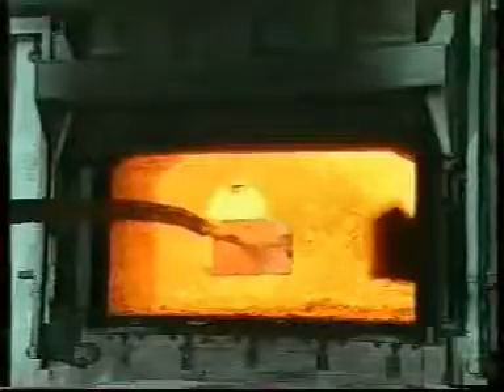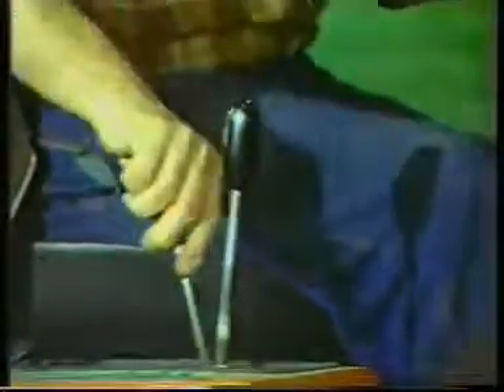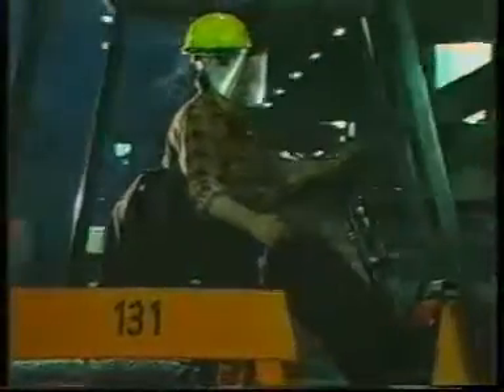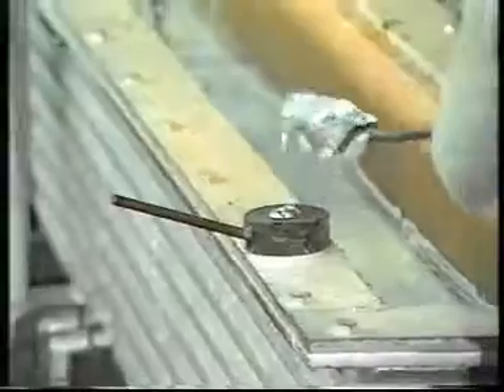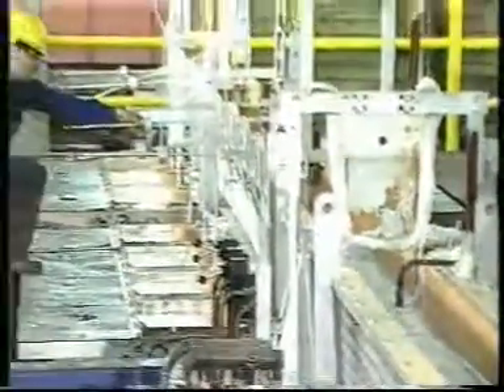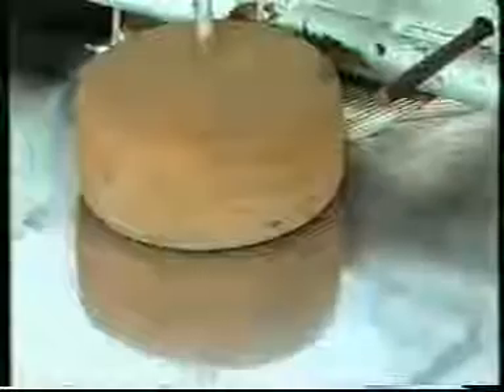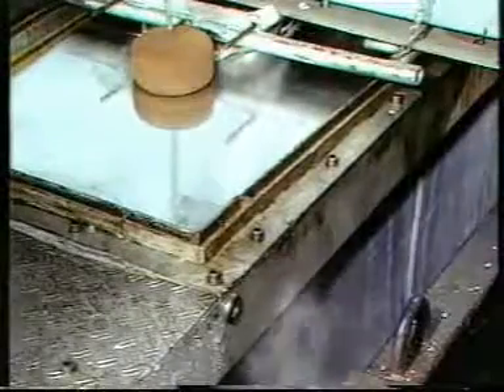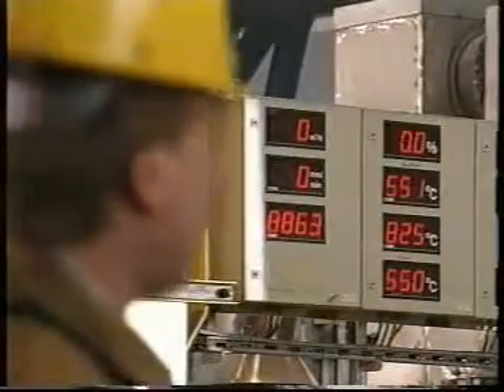The oxide formed during melting, the dross, is skimmed off the melt surface. At the end of this natural gas-fired process, the molten aluminium is transferred to holding and casting furnaces, from which it's cast into rolling ingots of the specified size. The dimensions of the cast ingots are 60 centimeters thick and up to 2.20 meters wide.